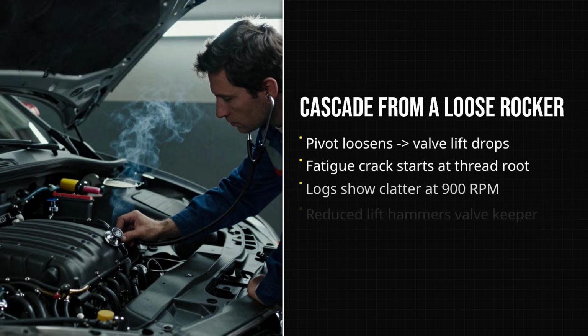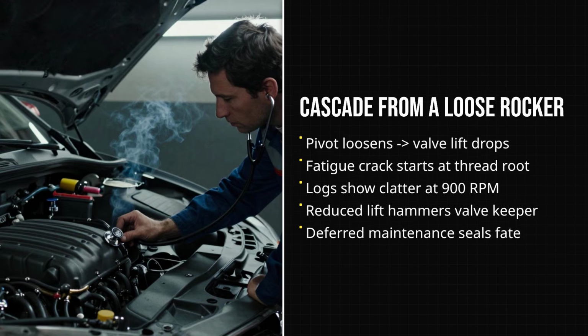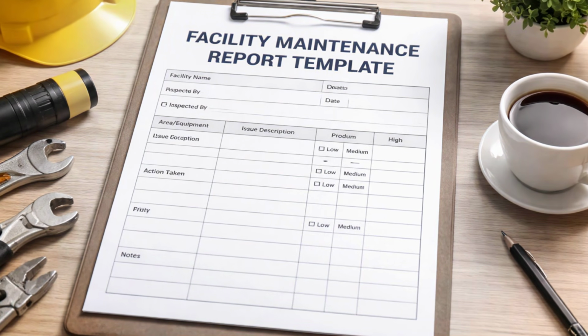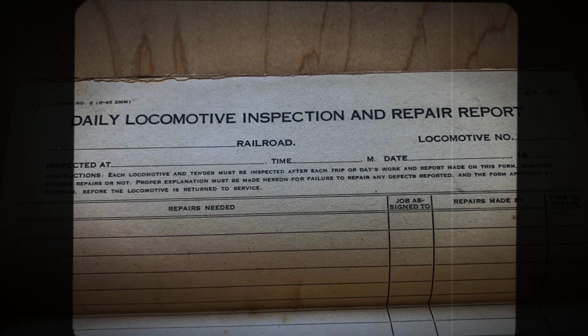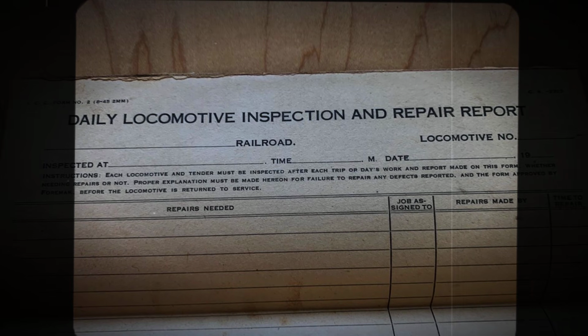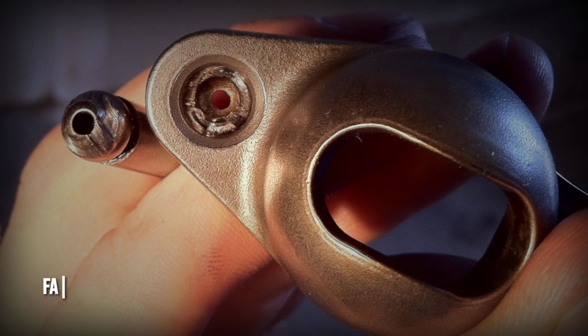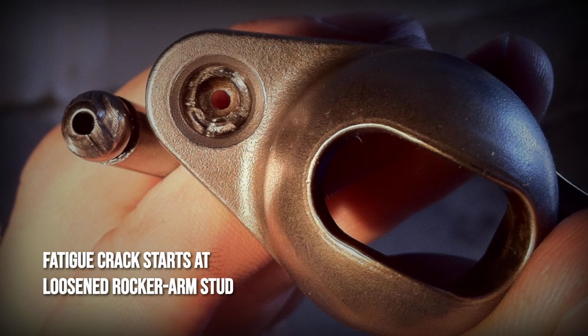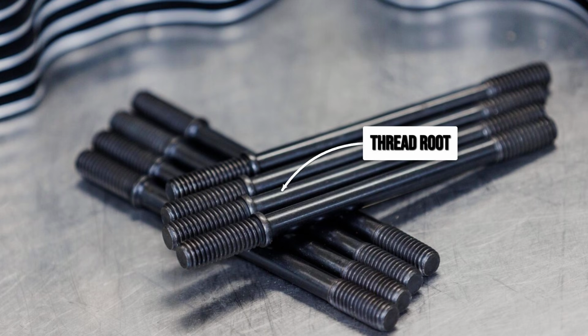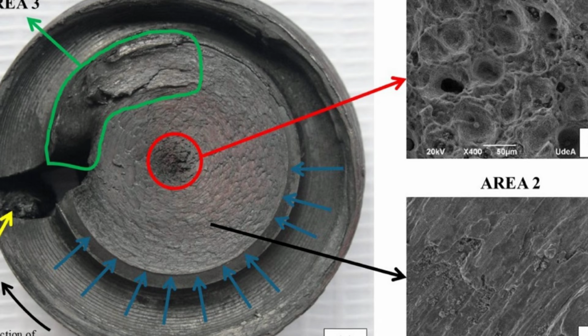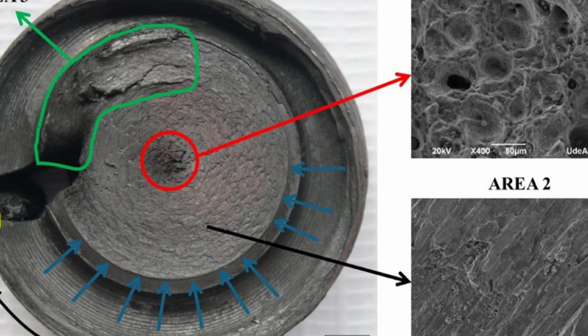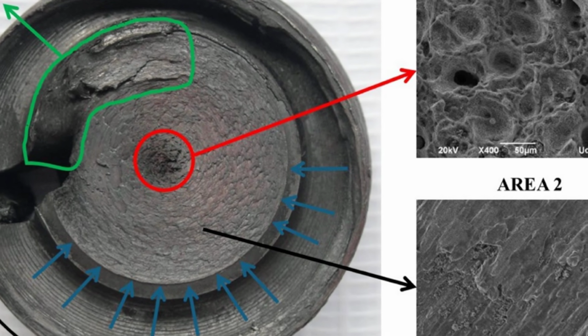Shop logs record recurring complaints: rocker pivot loose, audible clatter at 900 revolutions per minute, and deferred repairs because there was no immediate loss of power. The deferral is signed and the locomotive is returned to service. Fractography of the failed stud reveals a classic fatigue origin at the thread root. Beach marks radiate outward, each one a record of a running engine cycle.